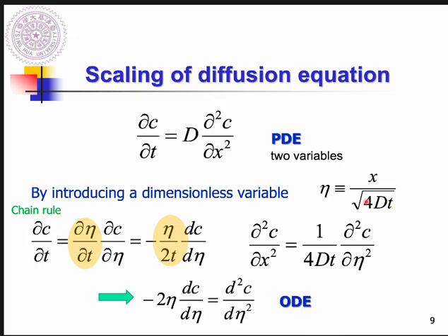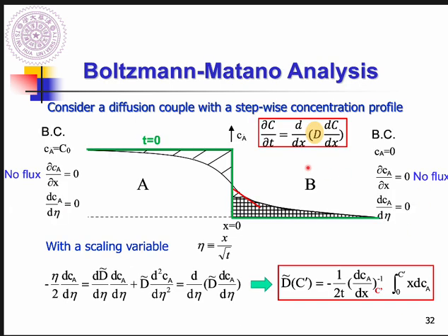But now you cannot use this eta, right? Because inside this eta you have a D, but as we mentioned, in this case the D is not a constant anymore. So at this moment, eta equals x divided by square root of t. This will help you to solve this differential equation. So we use eta equals x divided by square root of t, because we want to know the result D, so you cannot put a D inside.